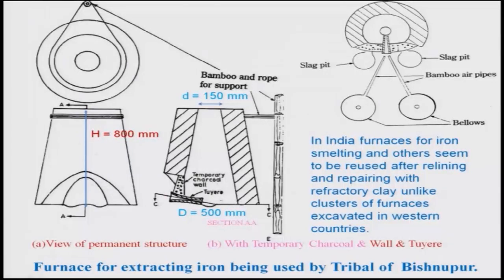For the air supply, there is a bamboo pipe. Taking the cross-section, the slag pits and iron blooms are visible. The tuyere pipe is connected with bamboo air pipes. Bellows were made of hide or skin, and people would jump on them rhythmically so that the diaphragm would move up and down, sucking air and pushing it through. These are the clay tuyeres — pipes through which air passes.